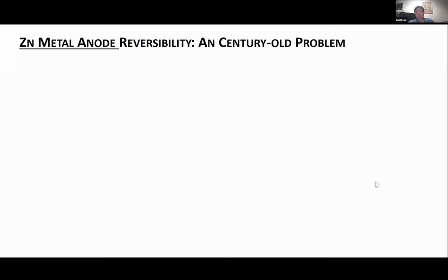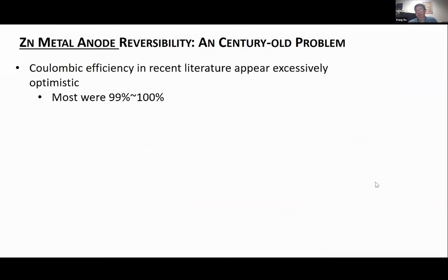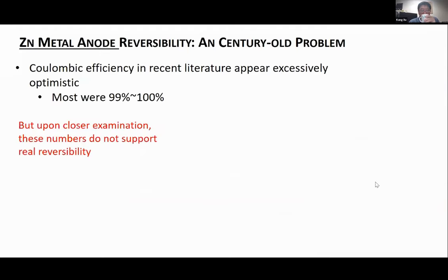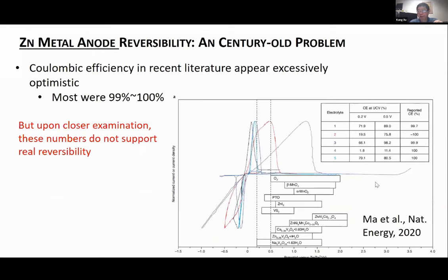So to use zinc metal as an anode, we have to study its reversibility. About 2 years ago, we started to pay attention to this. We knew that this is a century old problem, since the day of Alessandro Volta, because zinc has been known to not cycle very well, especially in the aqueous system. When we look at the data in the literature, we found that most data are very promising, 99 or over 100% quantitative deposition and stripping.